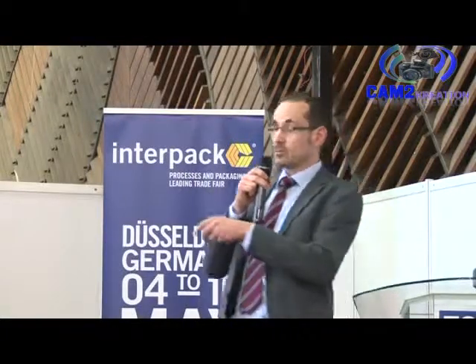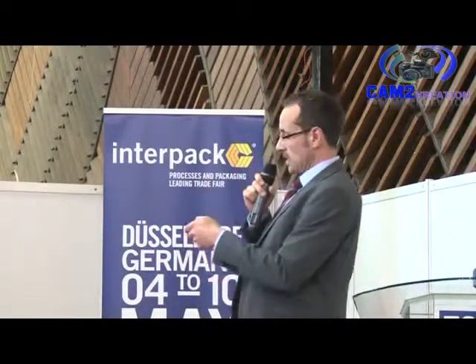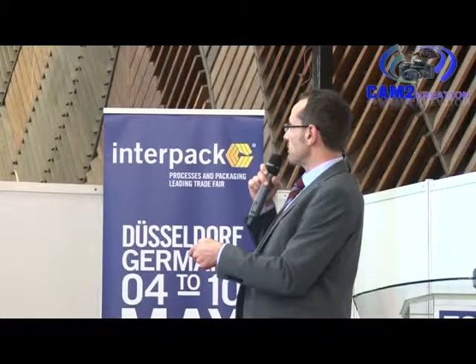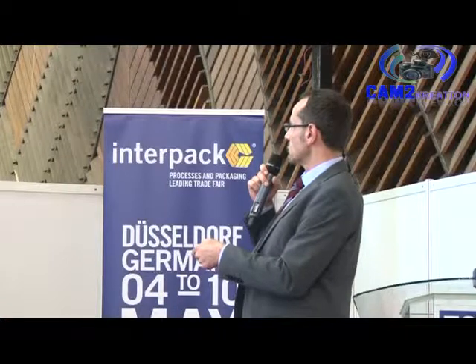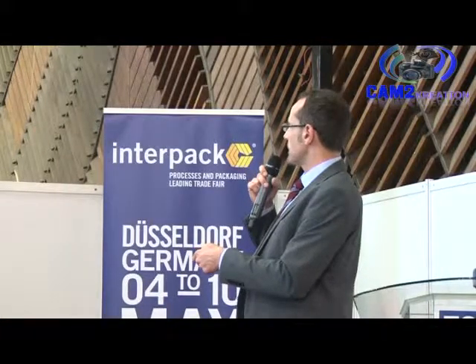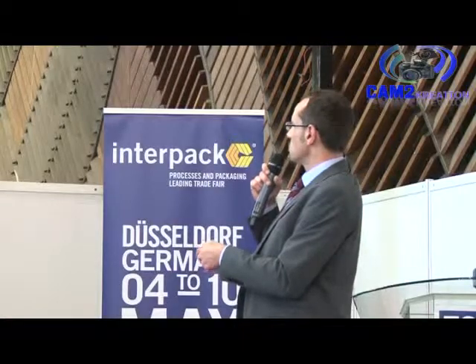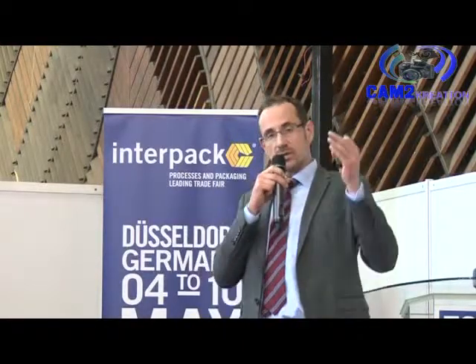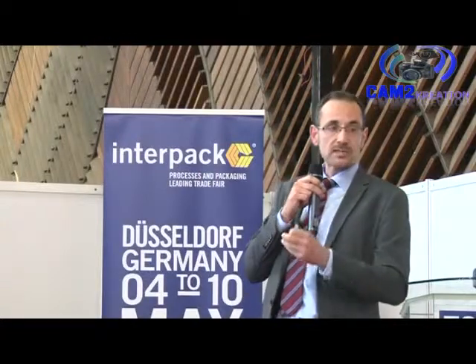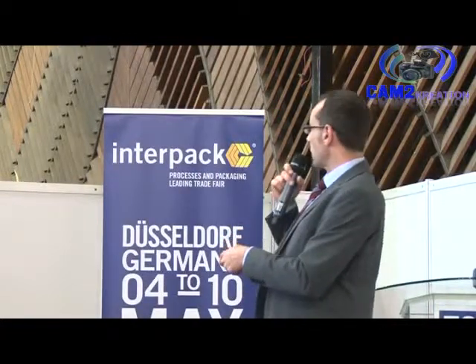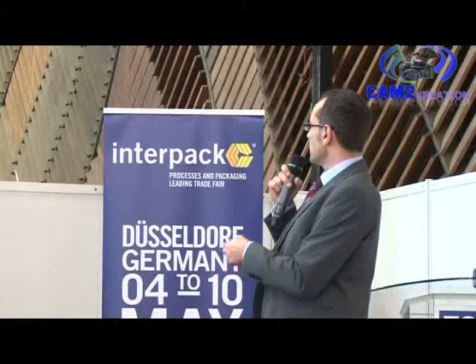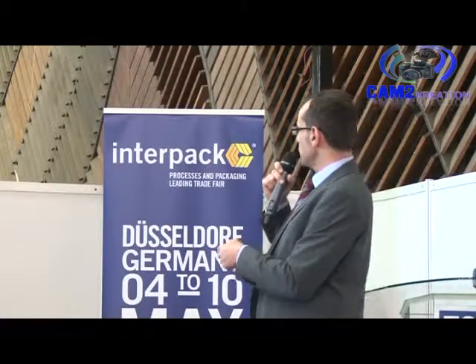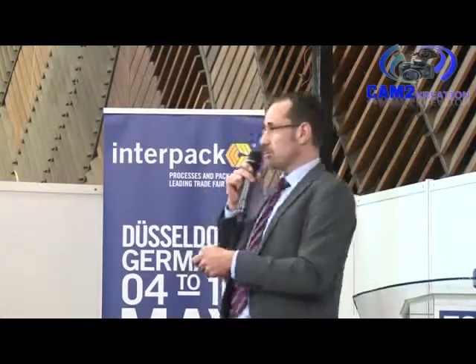We already gave you our brochures, so you have them. You can find the description of our grades, and even more. It's very difficult to put all the possible structures here. But if we are talking about co-extruded film, for example, a simple structure could be just polyethylene, adhesive resin, nylon, adhesive resin, polyethylene, or you can bring polyamide outside. As said, you can use higher sealing temperatures, and the packaging outside is more glossy. The typical range of this vacuum packaging is between 50 to 150 micron of total film thickness.